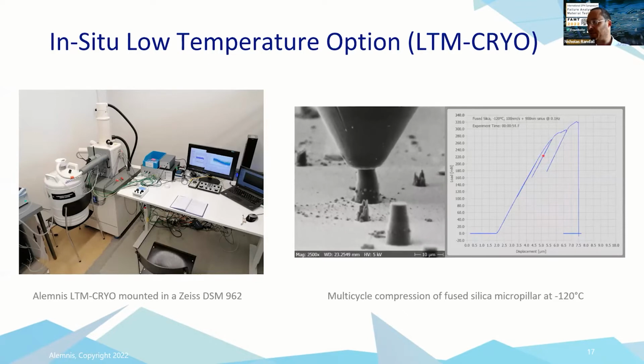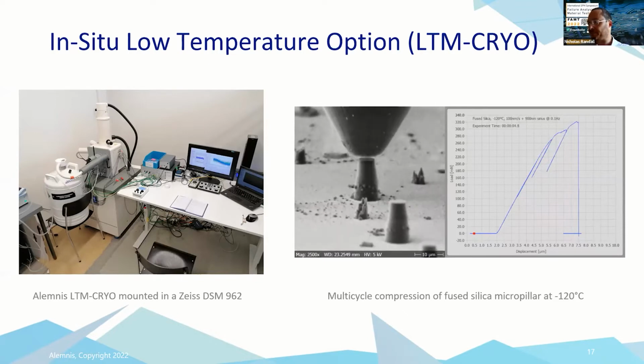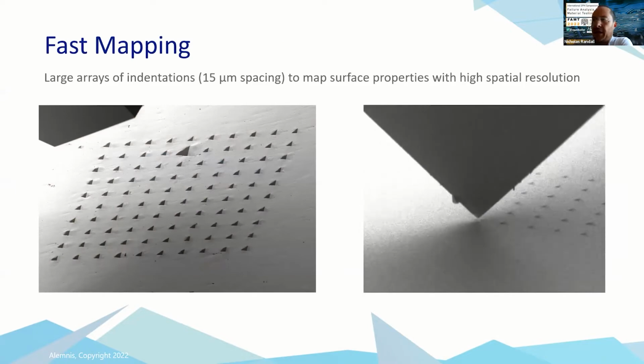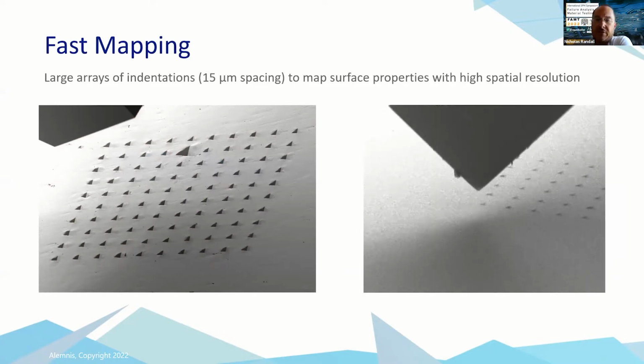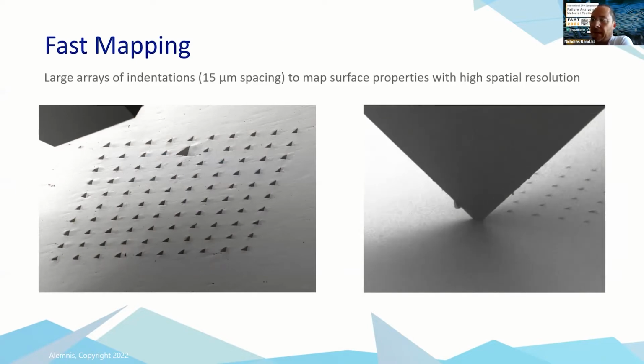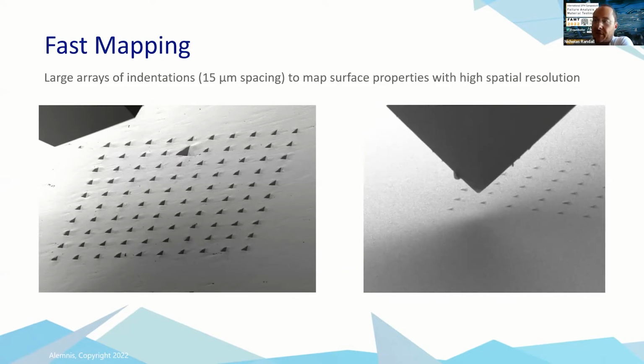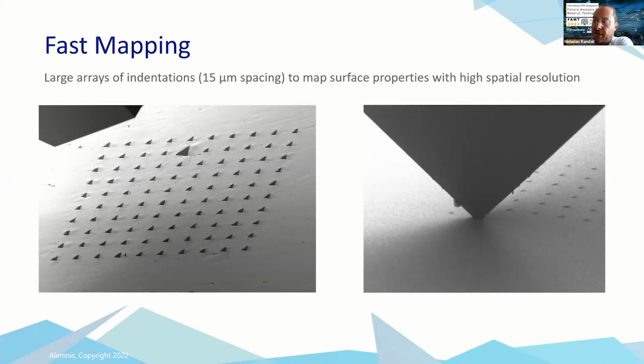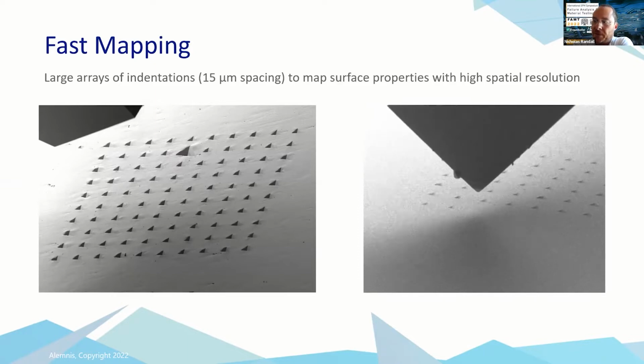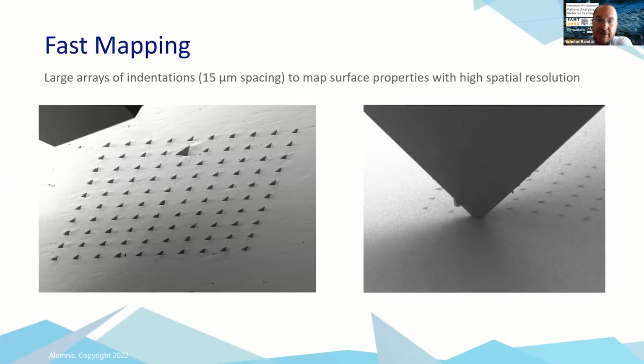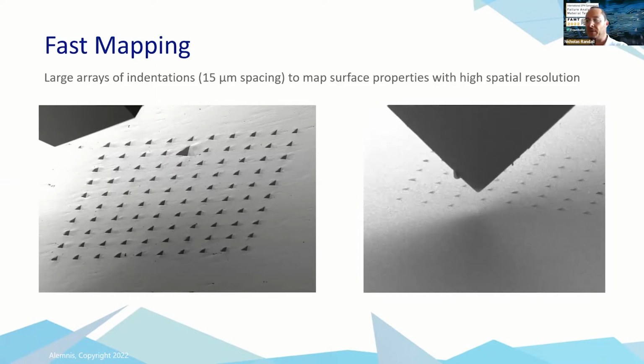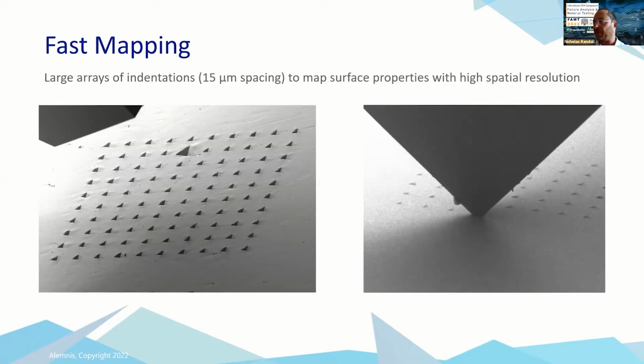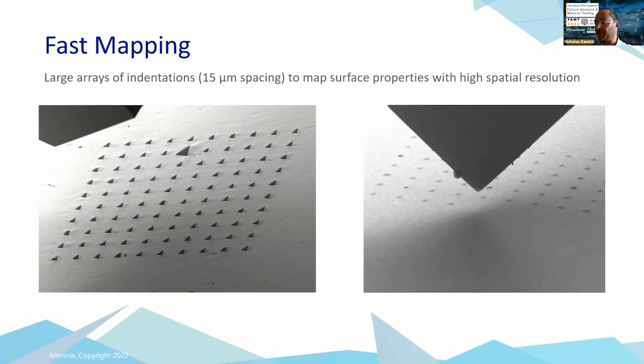So a nice example. Another recent innovation is high-speed mapping, so the ability to make large arrays of nanoindentations over a defined surface and actually see what's going on. We can do that because we have very fast electronics for the strain rate. So you can see a typical fast map being performed here with a Berkovich indenter.